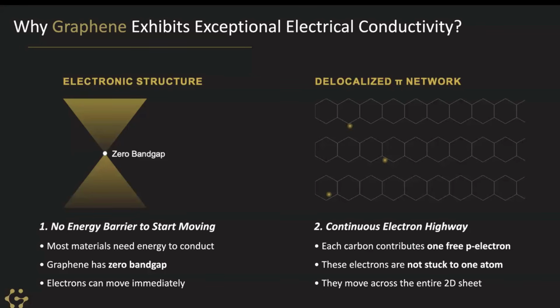But that's only part of the story, because as you remember earlier, we mentioned that each carbon atom forms three strong bonds, leaving one electron in a p orbital. Now, these p electrons don't belong to one specific atom. They are delocalized and they're spread across the entire sheet. So instead of isolated charge carriers hopping from atom to atom, you have a continuous electron pathway across a perfectly ordered two-dimensional lattice. And because the lattice is so uniform, electrons experience very little scattering.